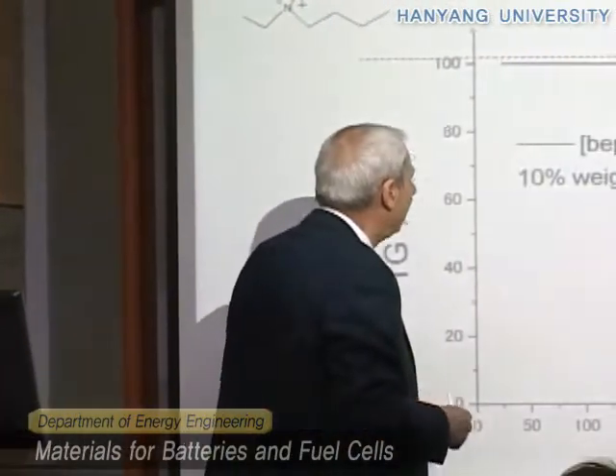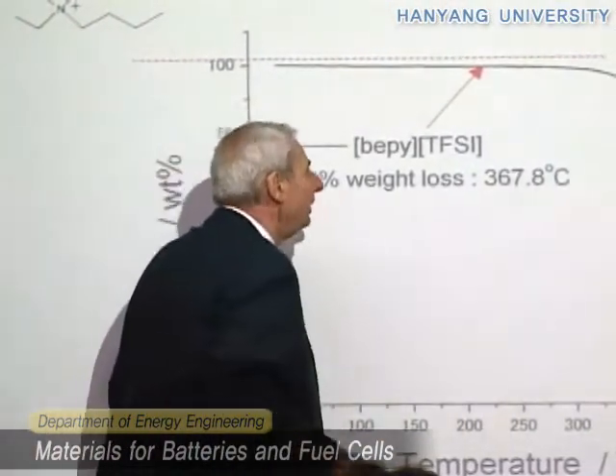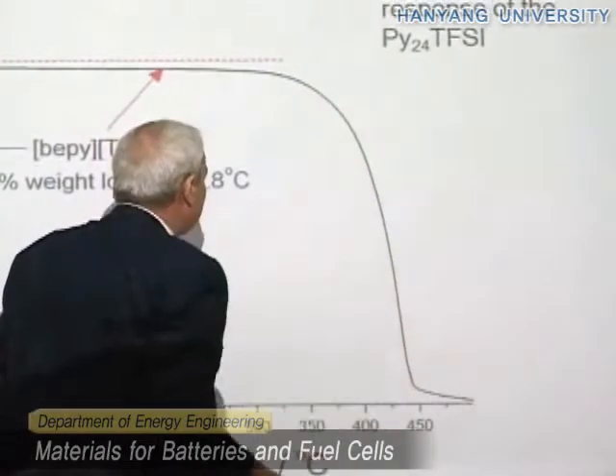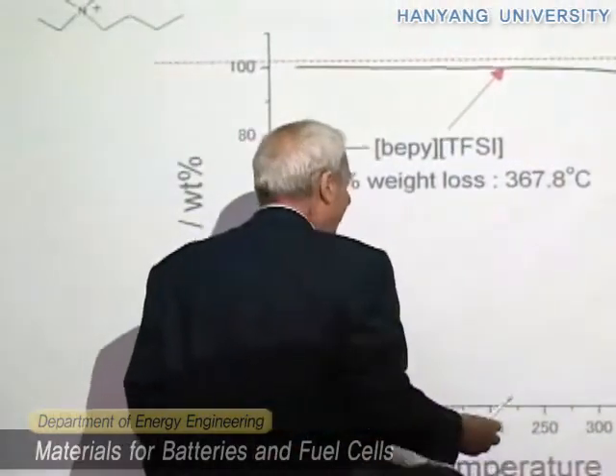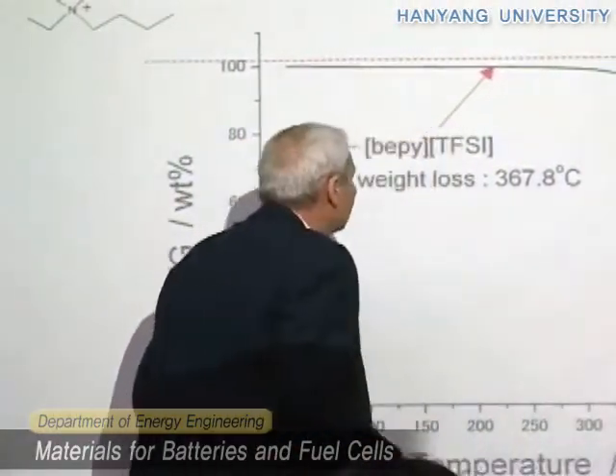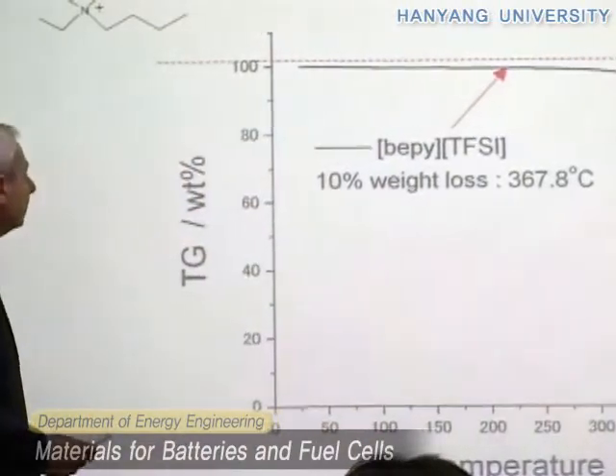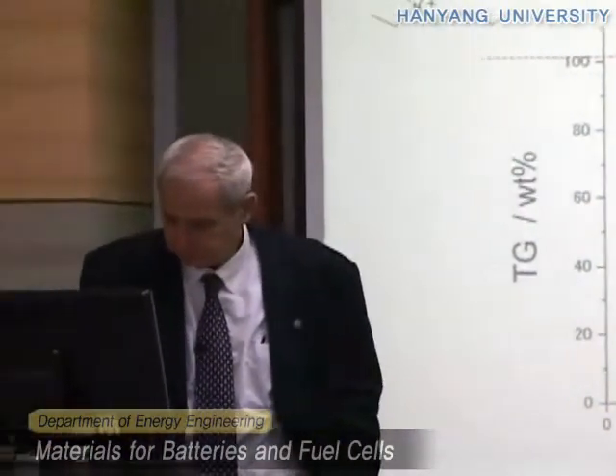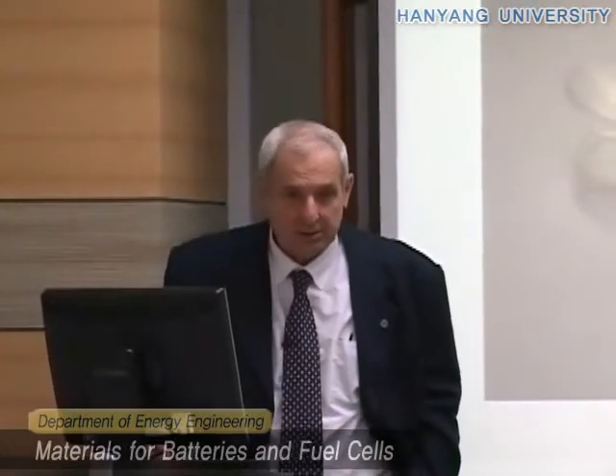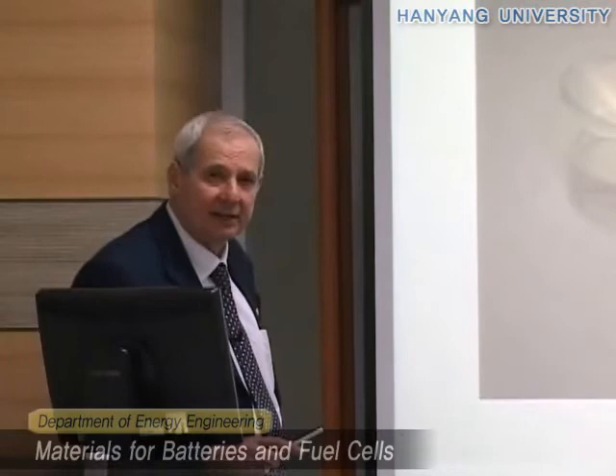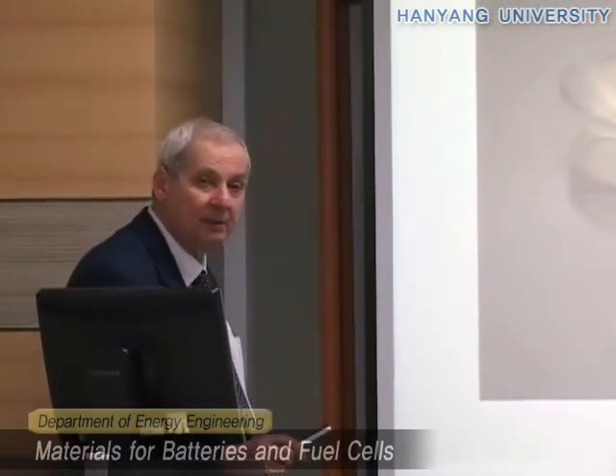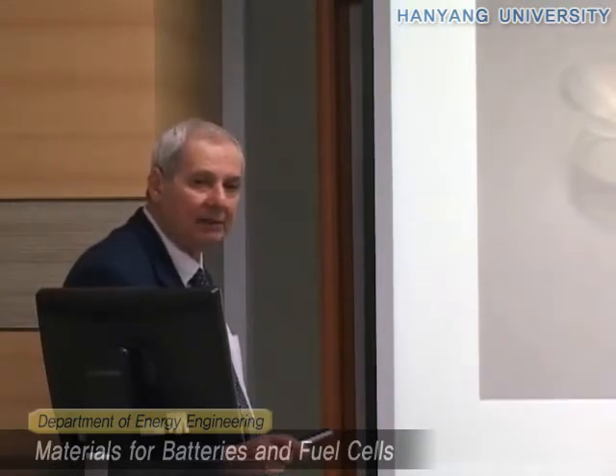And using one of these, maybe this one that we developed in our lab, you can see that we can go up to 350 degrees before you have any decomposition. And this is also demonstrated here. I think I showed this last year as well. You can use flame on this ionic liquid, nothing happens. If you do the same with a normal lithium battery solution, they go into flame.